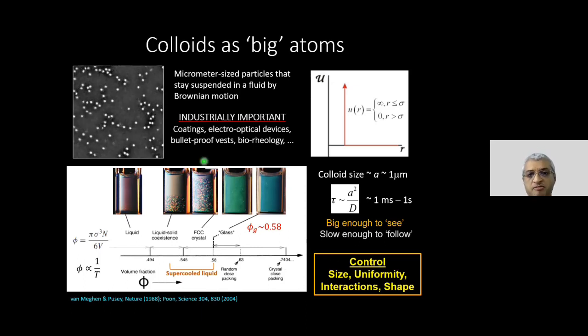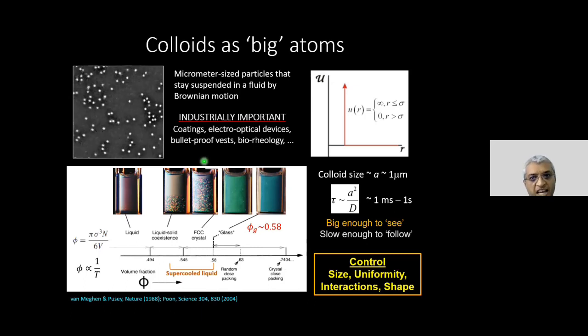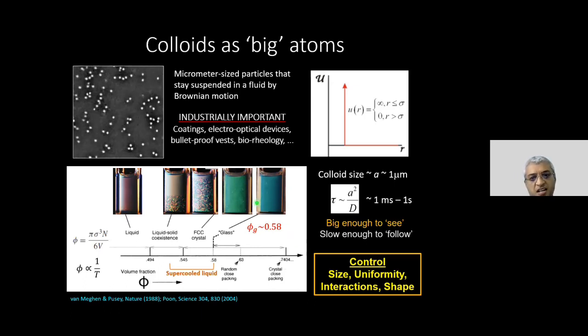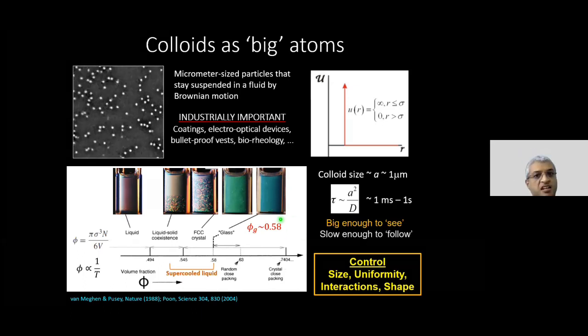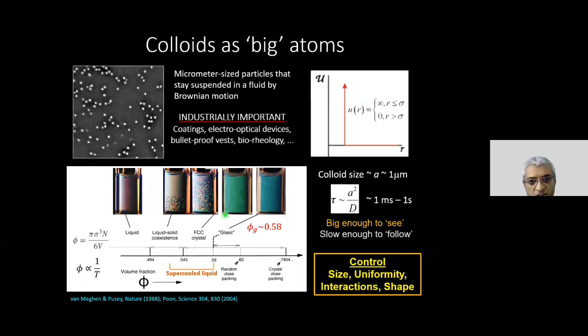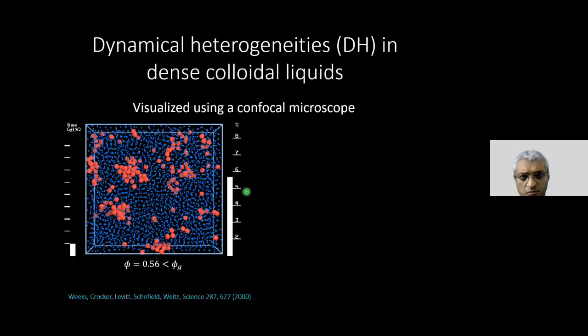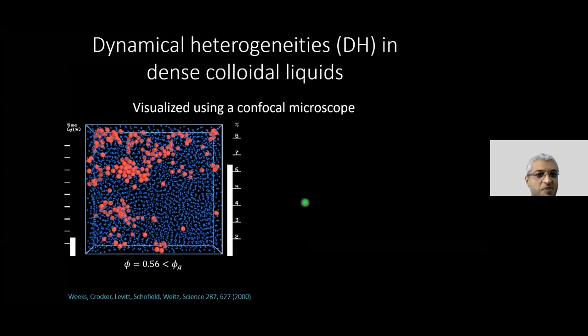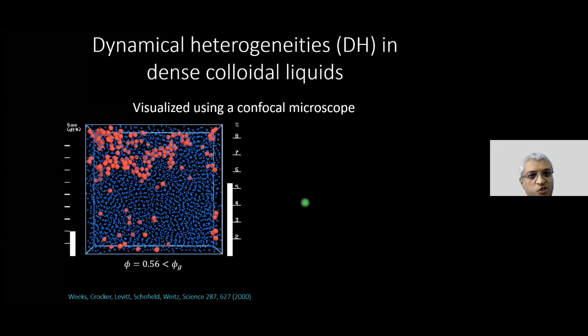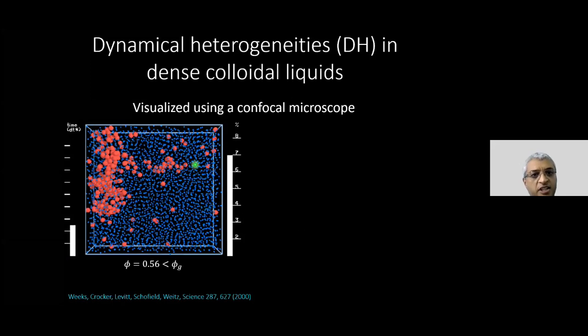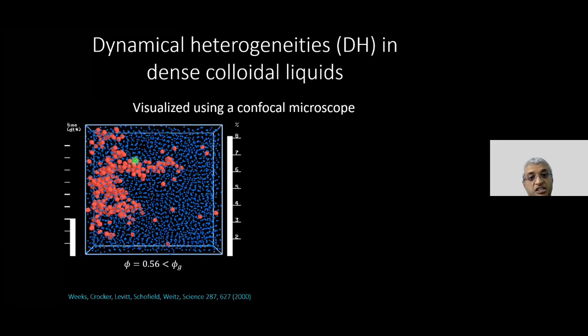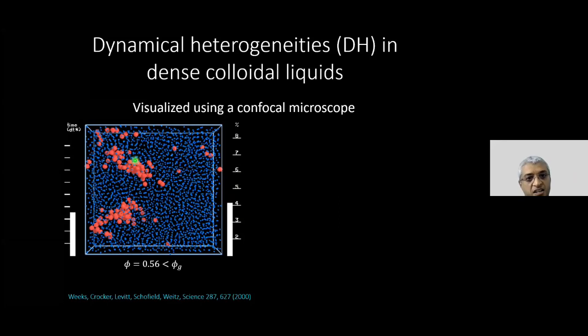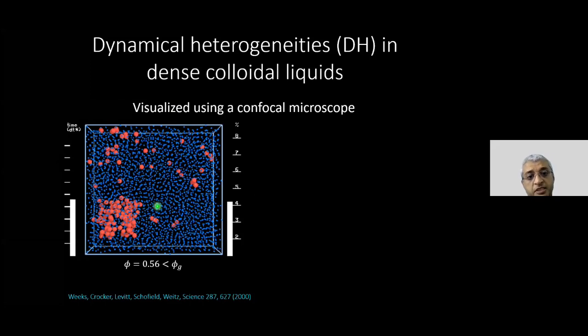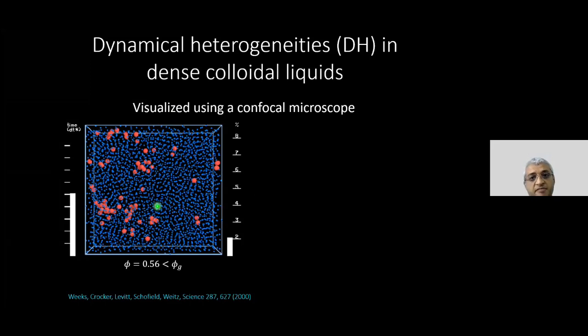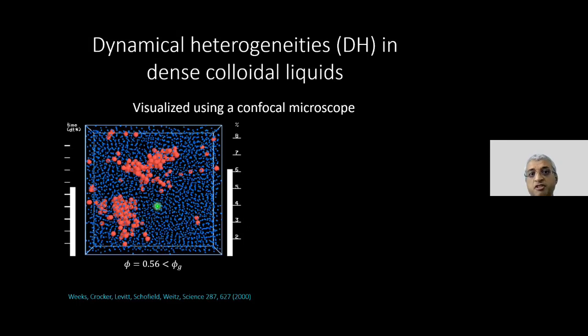Now, coming back to the problem of looking at these heterogeneities that were hypothesized but were never seen. What an experimental group from Harvard did is to basically take a microscope and look into the dynamics of what's going on in the sample, okay? And what they found was something that people had been saying for a long time, but it's always nice to see it in an experiment. What I'm plotting for you here is experimental data that's just being rendered using colors. What I'm plotting here are the top 10% most mobile particles. So I'm going to take my fluid, and I'm going to identify all particles in the fluid which were very mobile.